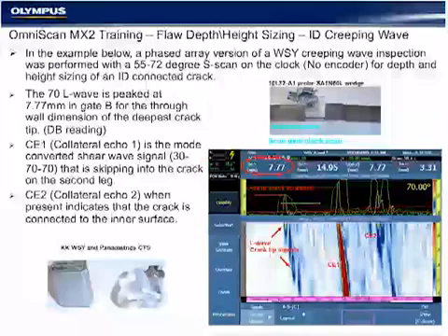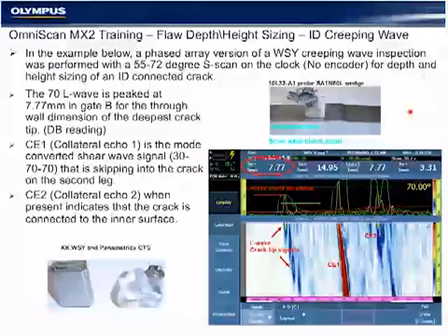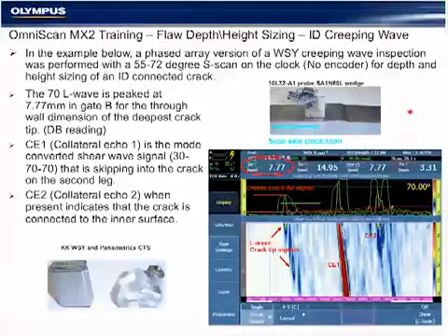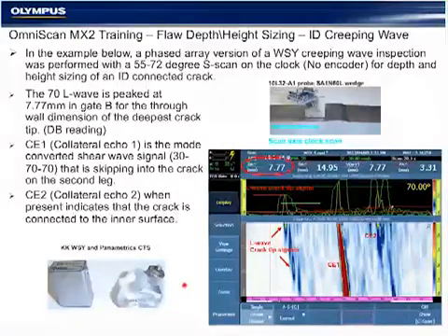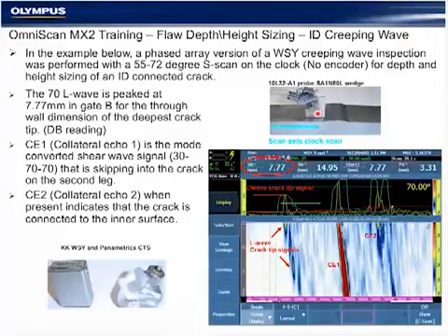Traditional techniques such as the Krautkramer WSY probe and Panametrics CTS probe are conventional depth and height sizing crack detection probes. Those techniques are reproducible in the phased array using an L-wave wedge. In this case, we're doing depth and height analysis on a crack by scanning the probe on a clock inspection towards the flaw until it's butted up against the weld and I hit pause.